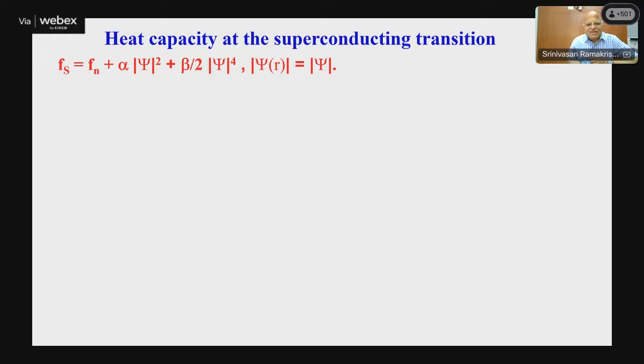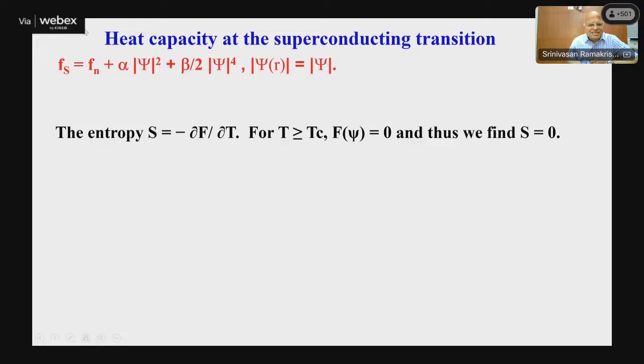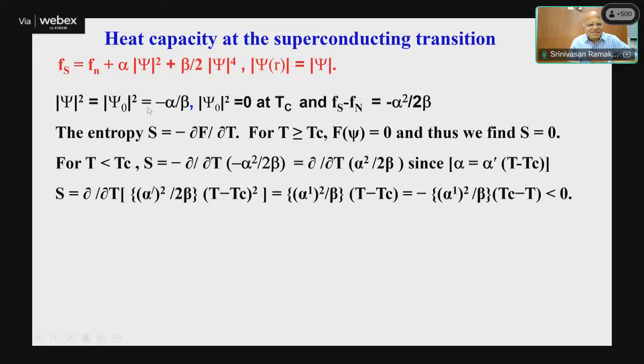And we can also calculate the heat capacity. The free energy is given by this expression. So psi naught squared is minus alpha by beta, and psi squared goes to zero. The order parameter goes to zero at Tc, and so the difference in the free energy is minus alpha squared by 2 beta. So the entropy is defined as the first derivative of free energy with respect to temperature.